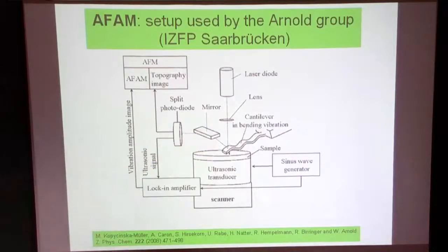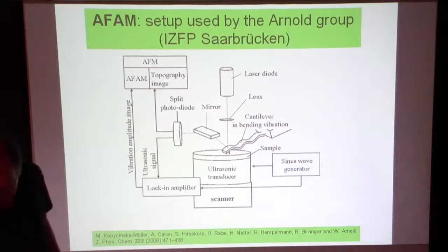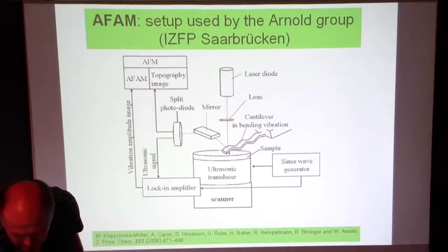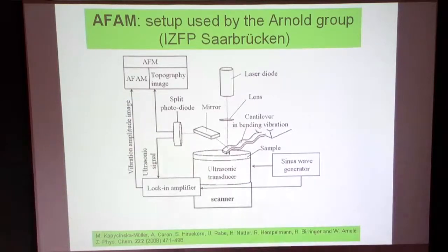And this way we get information about the contact modulus. So we measure locally, with the tip radius in the Hertzian contact model, the modulus of our sample very locally. Not on an atomic scale, of course. That's not possible. Because the radius we measure is about 10 times the radius of the tip, and if you think of the tip as a sphere, then you have a certain radius there, and 10 times that is your measurement zone, so to speak, and that's about 10 nanometers resolution. So what's the typical scale there? 10 nanometer. 10 nanometer, yeah.